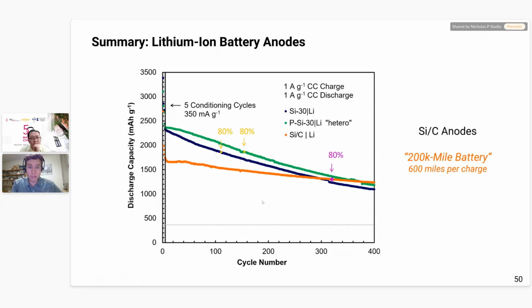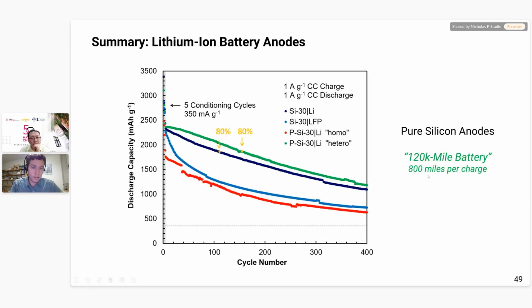And silicon can have certain advantages. Here's a trade-off. If you want a cell with double the energy density of a standard lithium-ion cell, this energy density includes all of the weight of all the other components, like the cathode, the cell casing, the electrolyte, everything else. You can see that even with 10 times the capacity, you still don't get 10 times the energy density. You get about twice the energy density, or double. But you pay a very heavy price for that because your cell now cannot last for 4 million miles. It can only last for 120,000 miles. So much reduced battery life, but each charge discharge cycle is significantly longer lasting.